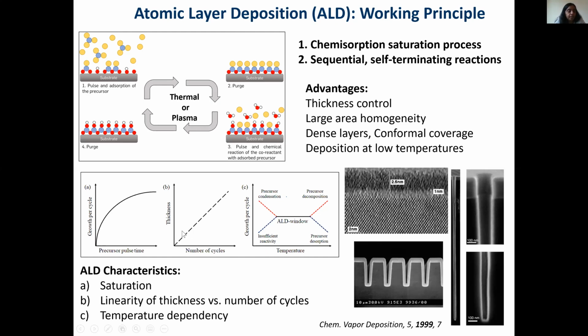So for example, 10 cycles, I have 10 nanometers, 100 cycles, I have 100 nanometers. So this is where you can precisely control the thickness. And when you have a precursor, which is a molecule that is brought in the gas phase, you have to make sure this precursor doesn't decompose. Otherwise, you may end up in a CVD process. So you have something called the ALD window, where the precursor efficiently reacts with the co-reactant and forms a thin film. And this is a range we actually operate in.